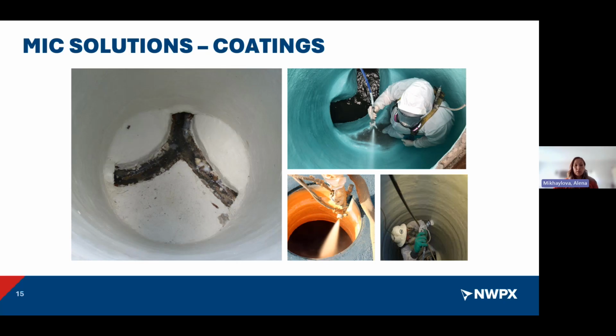This type of coating rehabilitation is ideal for emergency rehab, where you, let's say, are thinking about replacing your structure in 5-6 years, and you just want to prolong it a little bit longer. So this would be a good solution for short-term restoration. It's typically cheaper upfront, but if you're relying on this to prolong the entire life cycle of your structure, then it can actually become much more expensive, because on average, this type of lining can last anywhere between 5 to 7 years. So that's the average lifespan.